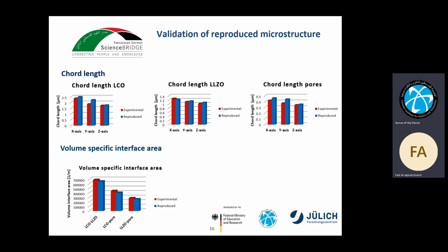The volume specific interface area between LCO and LLZO, LCO to pore, and LLZO to pore were almost matching between the experimental and the reproduced structure. It is very important for us because we have a hypothesis up to now that this is the factor that may affect the stress inside the system.